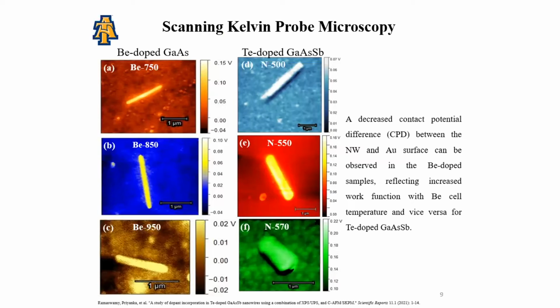Scanning Kelvin probe microscopy. SKPM scanning of the nanowire samples was carried out using lift mode, which uses 2 separate passes per scan line. The sample topography is measured in the first pass, while the surface potential is measured in the second pass.